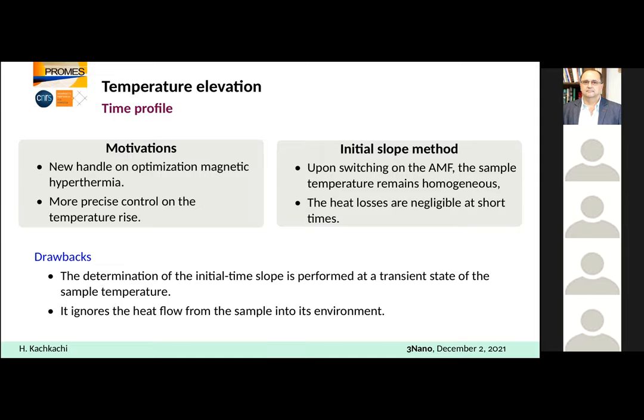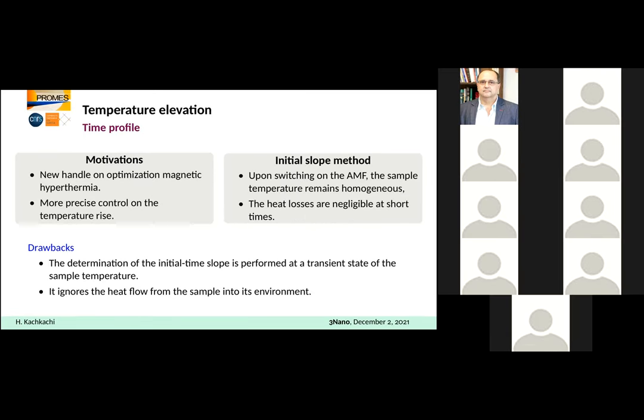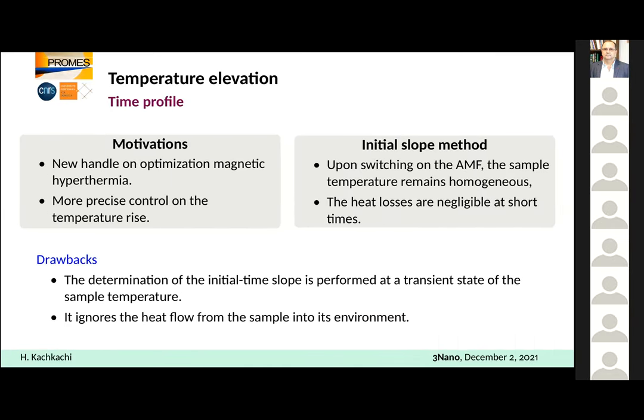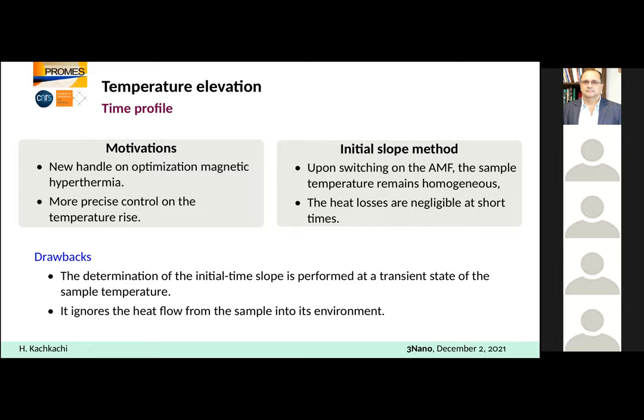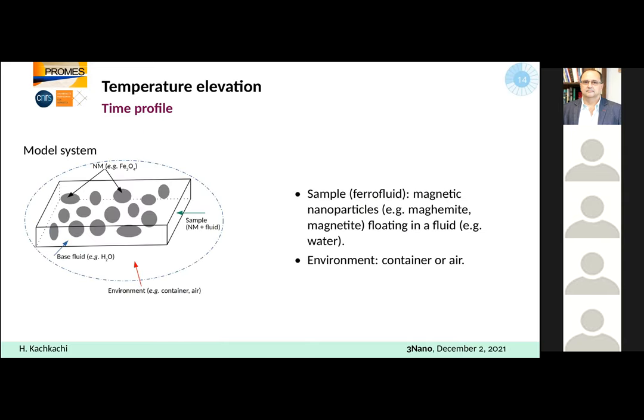The problem with it is that actually it is performed at some transient state of the sample. The sample hasn't reached thermodynamic equilibrium, and it's not so easy to define the temperature actually. And usually it ignores the heat flow from the sample into its environment, the loss of this heat to the environment, which one has to deal with, let's say, the process of the heat transport in such a system.